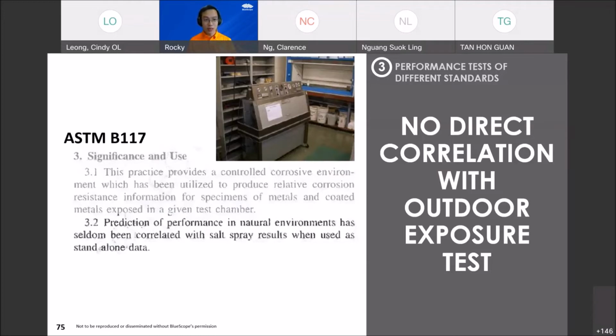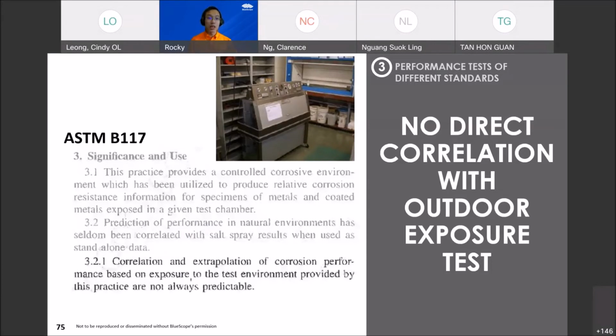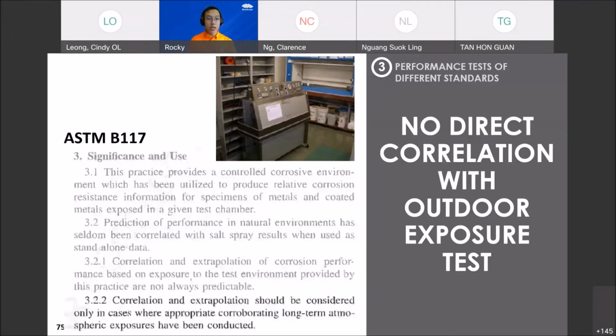meaning if you use salt spray test results as standalone data, it has seldom yielded a relevant result in a natural environment. And the correlation and extrapolation of corrosion performance based on exposure to the test environment provided by this practice are not always predictable, which later on I'll share some examples. And last, the correlation and extrapolation should only be considered if it has an appropriate level of corroborating long-term outdoor exposure data collected. Meaning, salt spray test by itself should not be taken as a realistic result unless it has a corroborating outdoor exposure test.